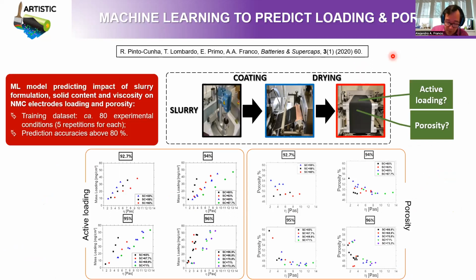You can also address the topic of slurries, coating and drying using machine learning. This is quite an old work that we published two years ago. But it was, as far as I know, the first one addressing this problem in such a way, I mean, using machine learning. Basically here, what we have done is we collect experimental databases. As an input, we were playing with the slurry formulation, the solid content, the viscosity, and we were measuring the impact of these three parameters on the active loading of the electrode and the porosity of the electrode at fixed drying conditions, right? So we collect this kind of data sets that you see here, they're very noisy, right? You cannot tell anything very clearly here.